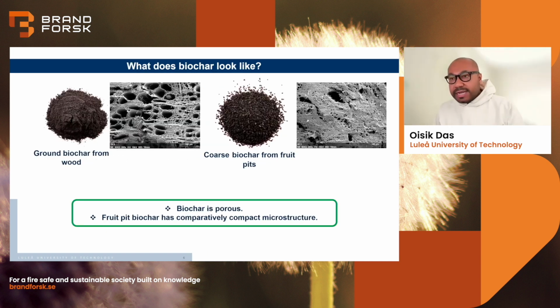So when I say porous structure, let's see what biochar actually looks like. We have two different types of biochar that we have used in the project. The first is a fine or ground biochar made from wood. On the right hand side, we see the image from scanning electron microscopy. The same we see for the coarse biochar, which was made from fruit pit, specifically olive pits. We see that both biochars are porous, so they have many pores and holes. And this is where the idea is: when this biochar is in concrete, can it allow water vapor or moisture to escape when concrete is being heated up?